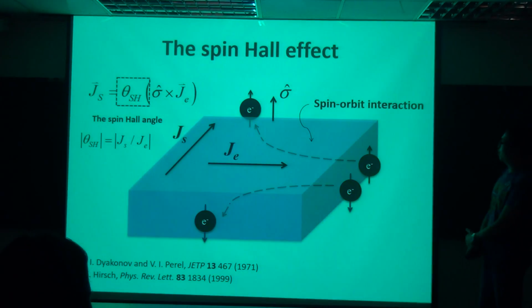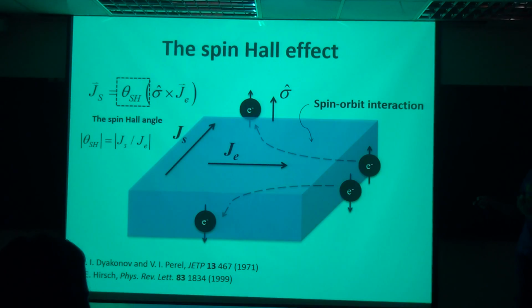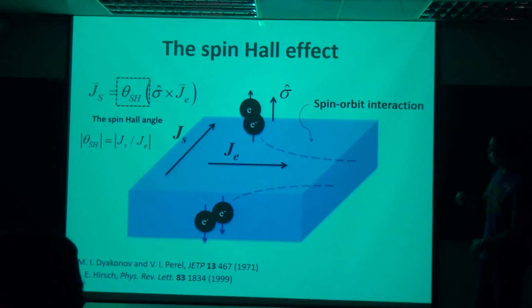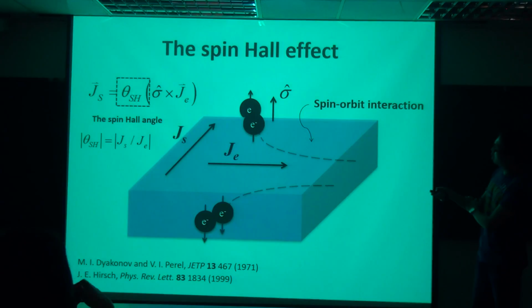Basically, the spin Hall effect comes from the spin-orbit interaction. If you consider a normal metal, for instance a transition metal like platinum or tantalum, and you send current or electrons through this material, then you will have charge current, of course. But at the same time, due to spin-orbit interaction, electrons with different spins will be deflected to different edges. So there will be spin accumulation and charge accumulation at the same time at the edges of the material. And this will give you a spin current, and the spin current will depend on the spin polarization direction of the electron and also the charge current direction.